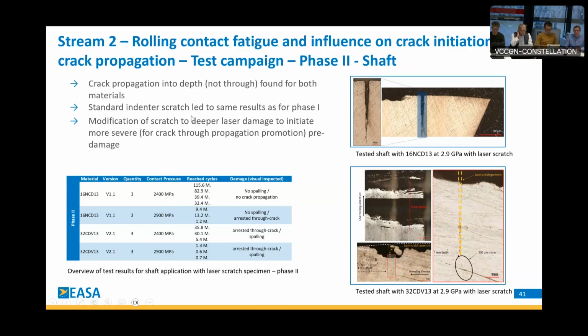But this just led to the same damages as before, spalling, so nothing else. To provoke a crack through in the part and, let's say, help the part to be more critical, we decided to modify the scratch and add a deeper damage by laser to initiate a more severe crack initiation, to have the crack-through propagation promotion as a pre-damage.